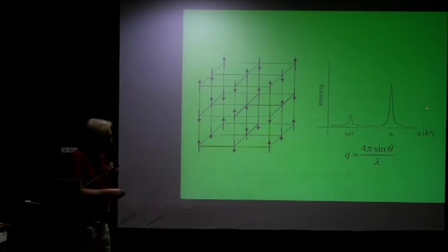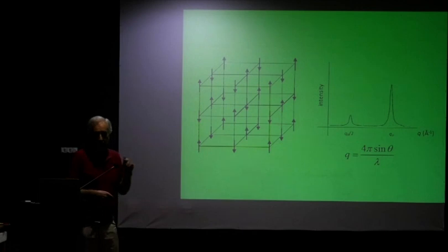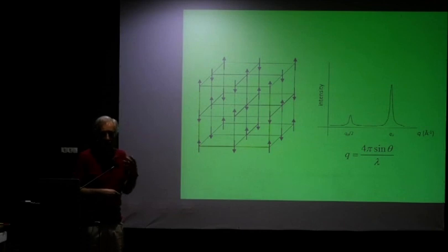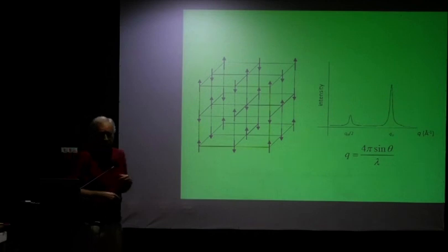And what happens is that here you see the appearance of another peak, which is purely magnetic in nature. It's not the structure, but this peak comes out as a magnetic superstructure peak at half the value, in this case, of this Q0 over here, of the structural peak.